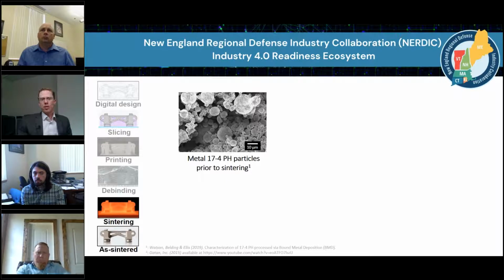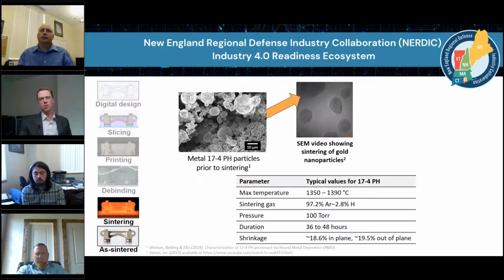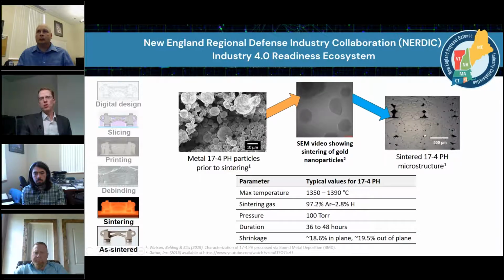After they come out of the debinder, they go into a sintering step. So here is an SEM. After you heat up to about 150 to 200 degrees C, depending upon the binder, the binder will evaporate and you're left with just metal particles. So here's the metal particles right here. As we continue to heat up to around 1350 or so, the sintering process will take place. Here we have those particles and they'll fuse together in solid state sintering. And whenever it's done, what we end up with is a microstructure on the far right. We'll look at that some more in the next slide to come.